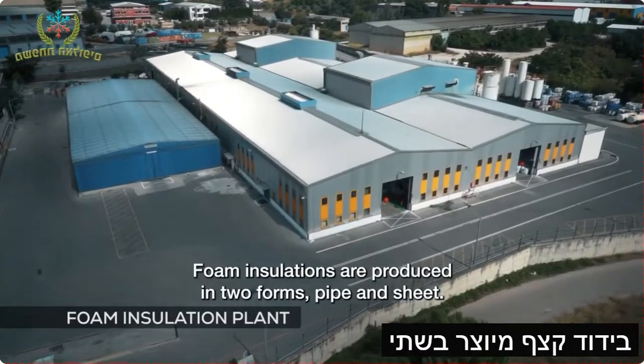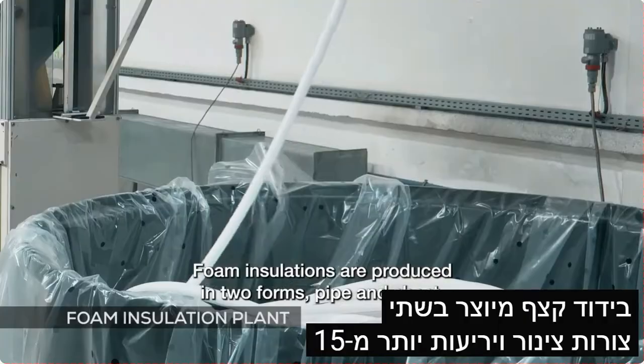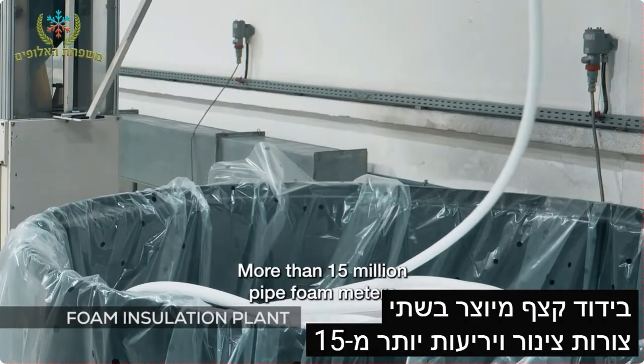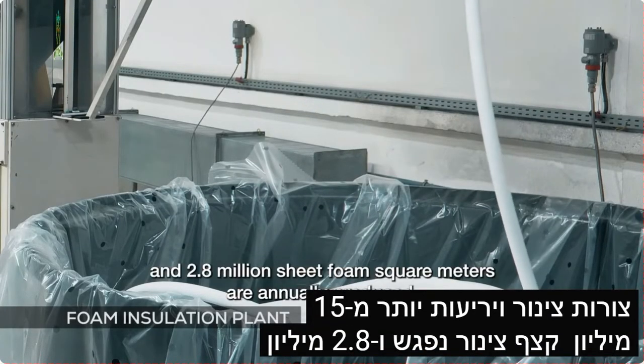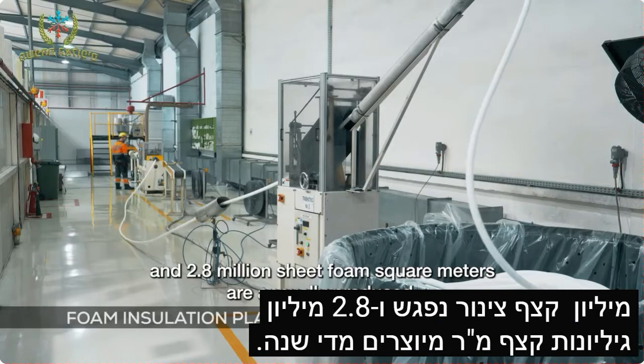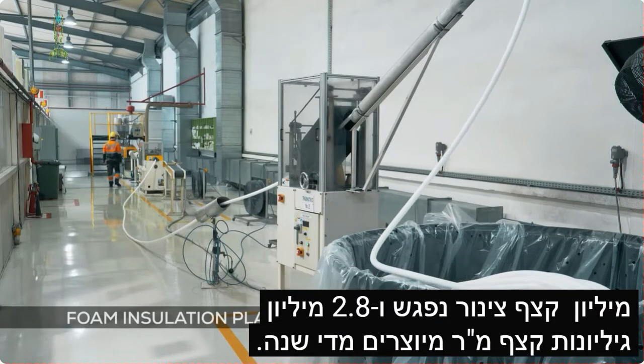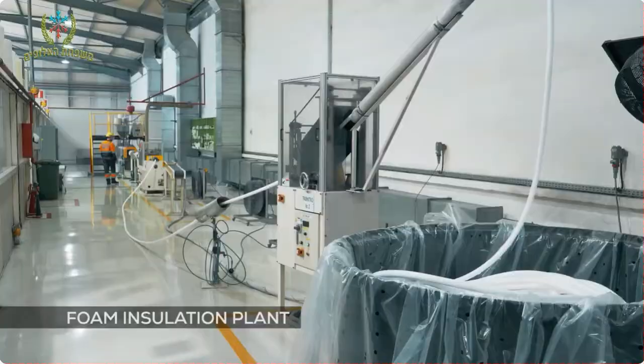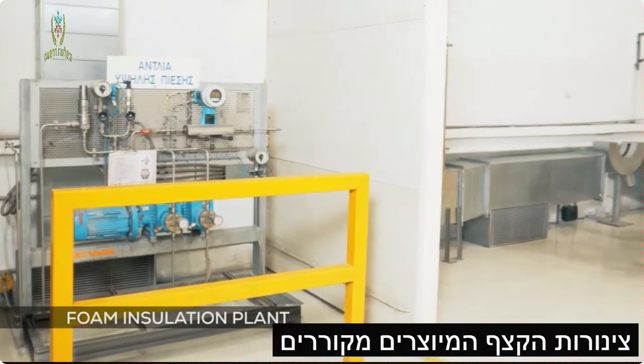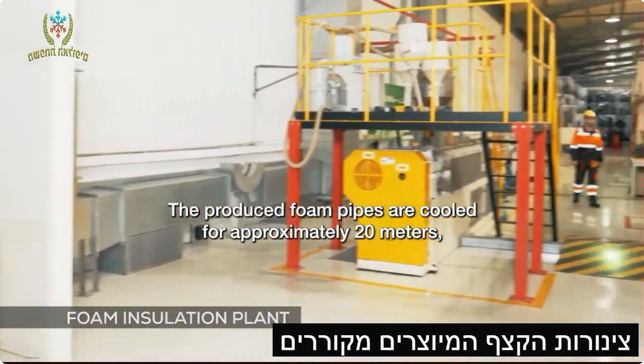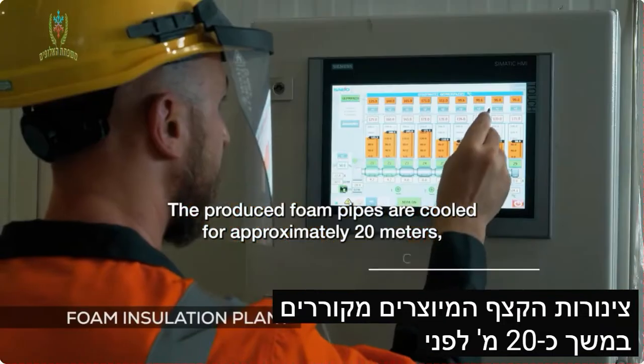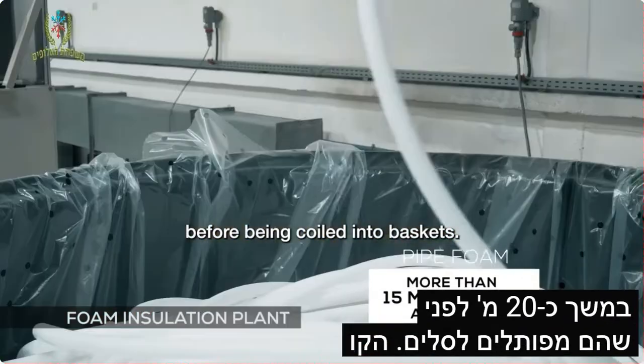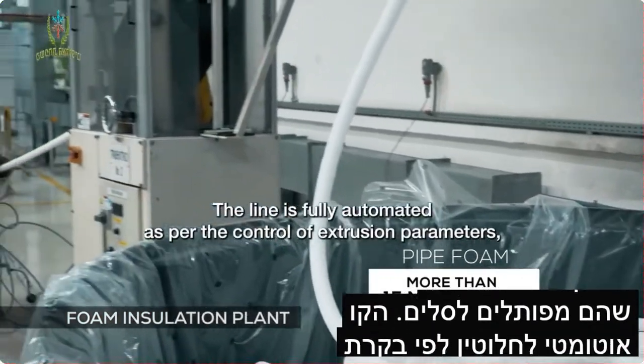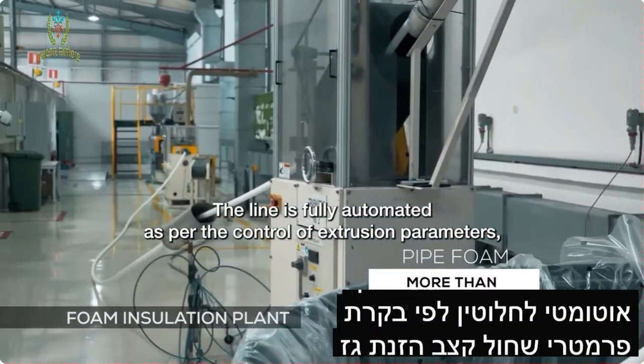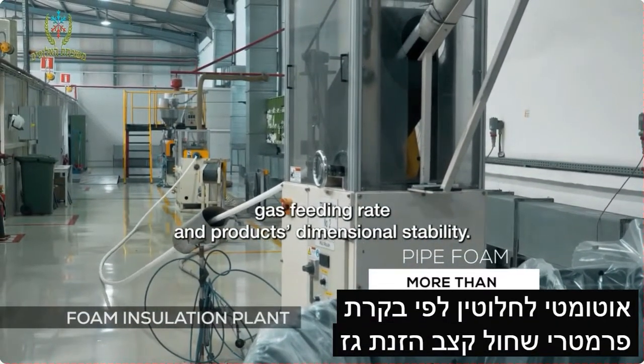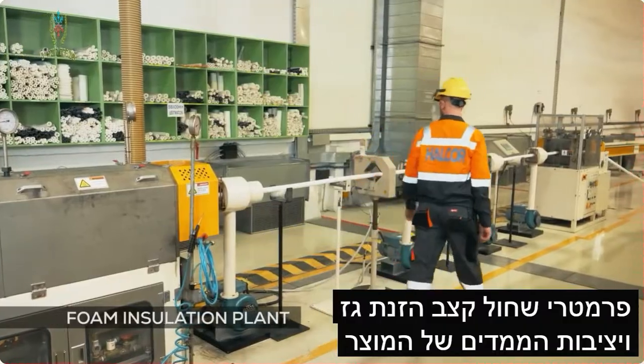Foam insulations are produced in two forms, pipe and sheet. More than 15 million pipe foam meters and 2.8 million sheet foam square meters are annually produced. The produced foam pipes are cooled for approximately 20 meters before being coiled into baskets. The line is fully automated as per the control of extrusion parameters, gas feeding rate, and product's dimensional stability.